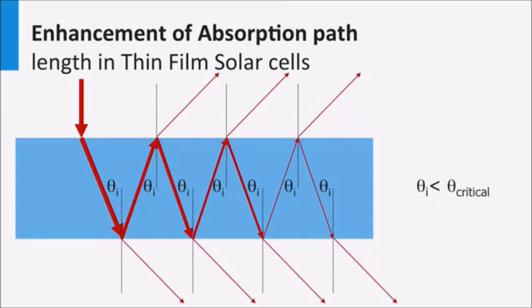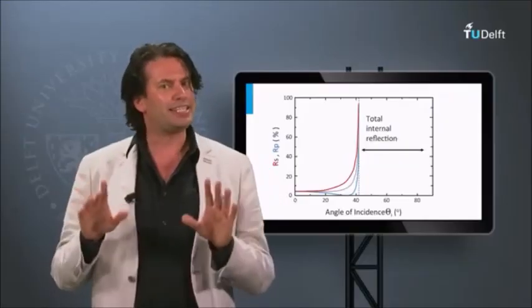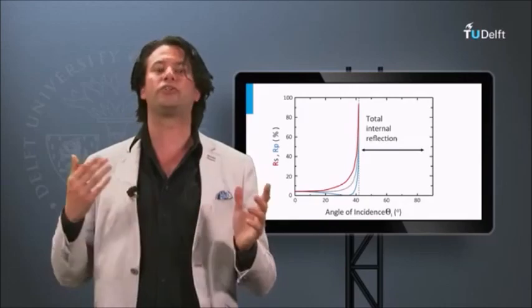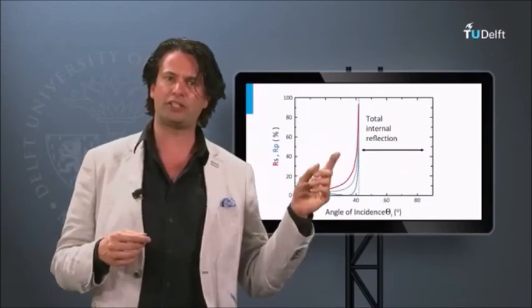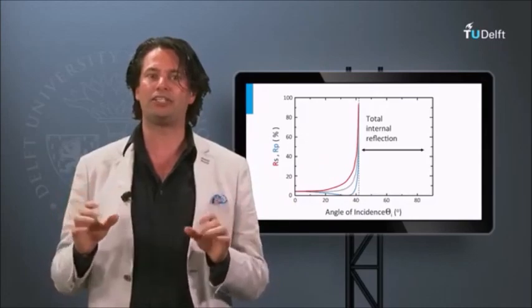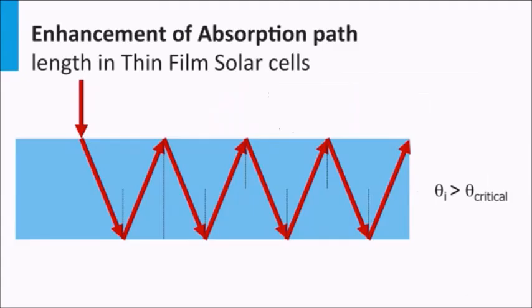The light is scattering between the two interfaces, down and up. In the ideal case, you would like to have all light trapped in the absorber layer, making the absorption path length so long that all the light is absorbed. Unfortunately, at every internal reflection, part of the light is transmitted out of the film. However, this is not the case when there is a total internal reflection. From the Fresnel equations, we know that above a critical angle, the internal reflection becomes 100%. This means that if the light is scattered into the film above a critical angle, the light would be trapped.